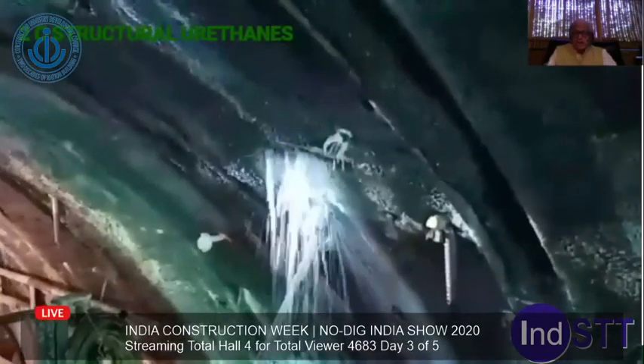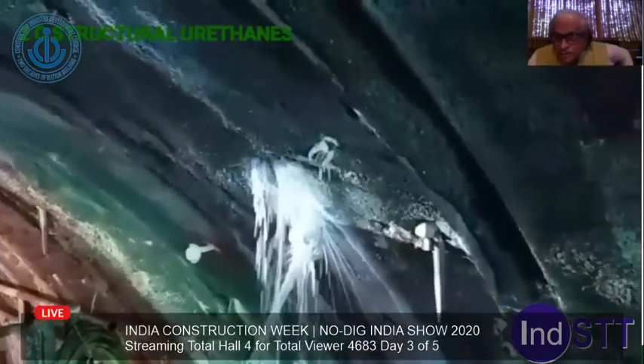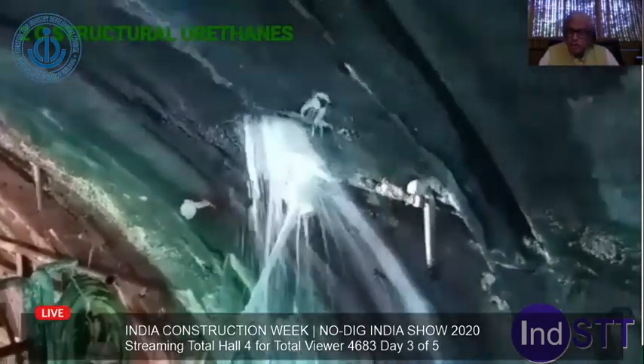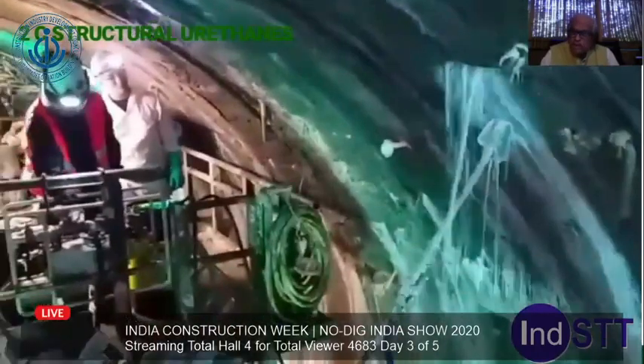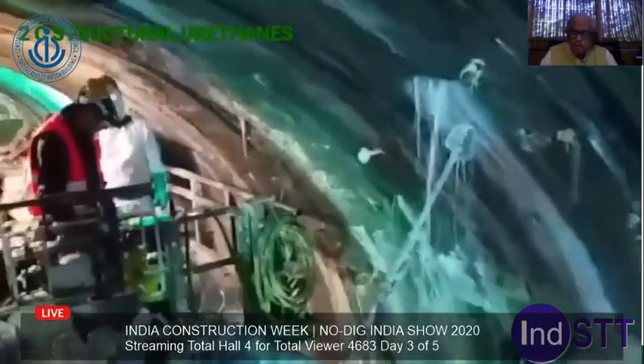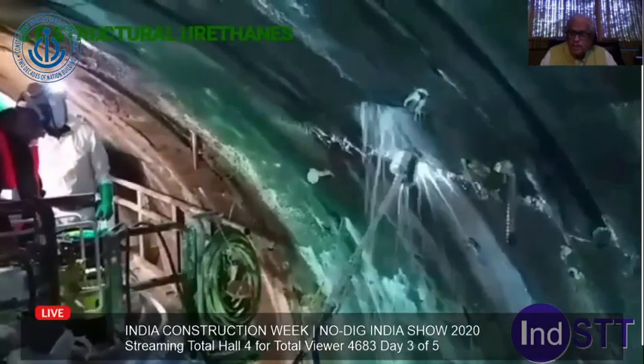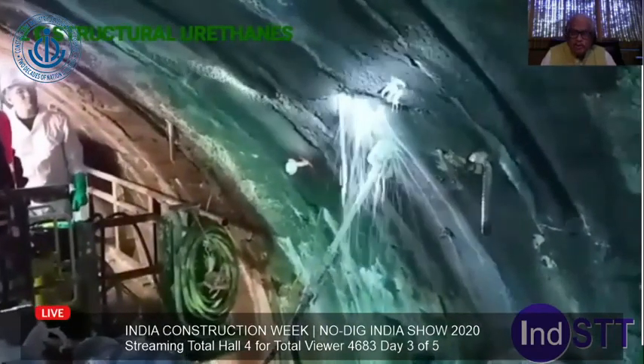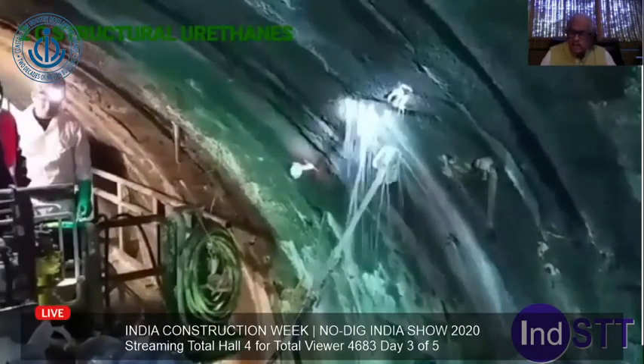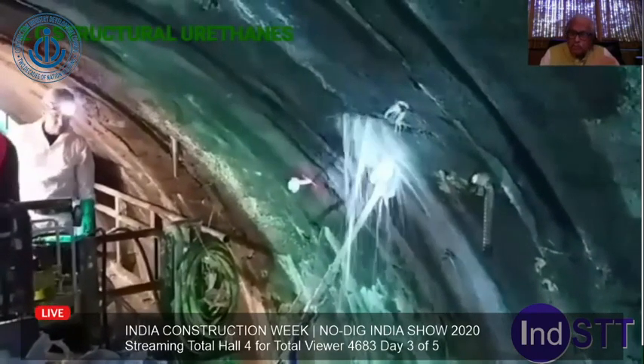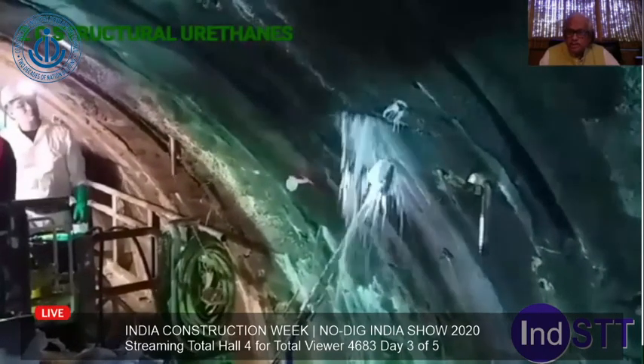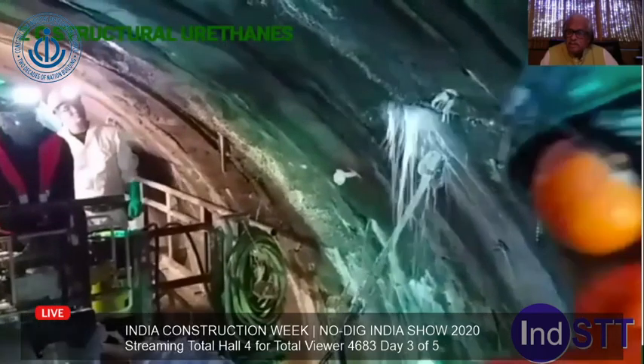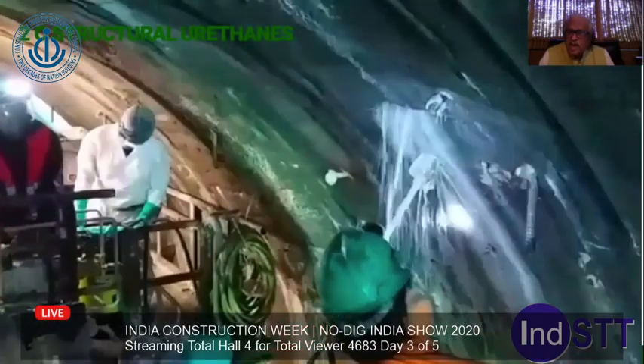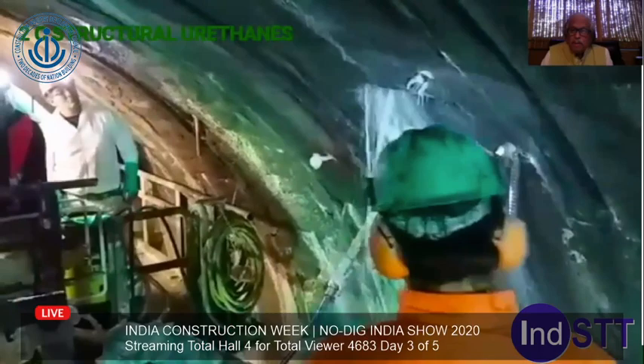For example, this is the type of water. You can try to put any foam inside which expands 50 times or 40 times. It cannot stop the water. Because to stop this type of water coming under such a pressure of 6 bars or 10 bars, you really need polyurethanes which are structural, which can harden totally underwater within a period of 1 to 2 minutes. So your construction can go on unabated, and it forms a permanent seal.